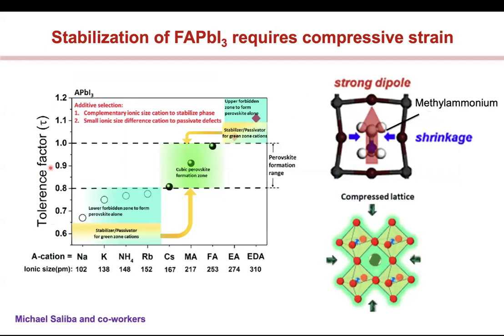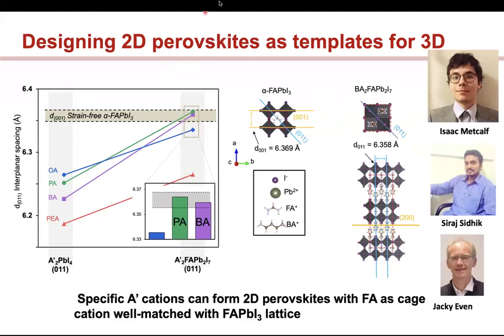And in fact, you can talk about this in terms of this tolerance factor. You see that this FAPI is right up here, right on the edge, and cesium lead iodide is right on the bottom edge. And so you have to think about a way in which you can compress this lattice, right? You apply strain on this lattice, so you push this down a little bit so that it falls into this green zone, and you can get a stable perovskite. Okay. And so that was sort of the idea that if you could do that, then you could stabilize this phase. And this is nice because FAPI is really temperature stable. And so we thought that this could make a really nice perovskite. And so we developed this design principle.